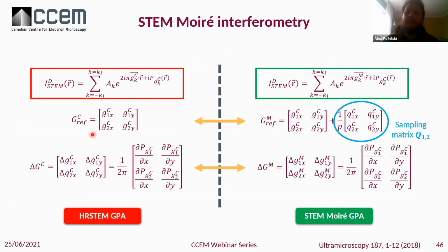I won't go exactly into the detail of that, but to do this undersampled approach, this large field of view approach, the delta G is absolutely identical. The only difference here is the definition of the reference. So here you can see no sample, you have nothing. Here you need to bring a small correction, this sampling matrix. So a small input that you need to add to be able to just go and use this undersampled micrograph at a large field of view.